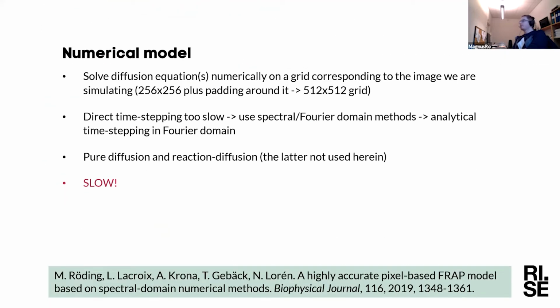So we have a numerical model for doing this, and I'm not going to talk about the numerical model, but basically it's a diffusion equation that we solve because it's a physical diffusion equation of sorts that we are observing. So we solve the corresponding numerical equation, and we do it on the same grid that the image is defined at, at the same resolution. We do that using some Fourier domain method, so it gets reasonably fast, but it is still rather slow. So if you would do the conventional thing, which would be least squares fitting, it might take a few minutes if you have a few data sets and so on.